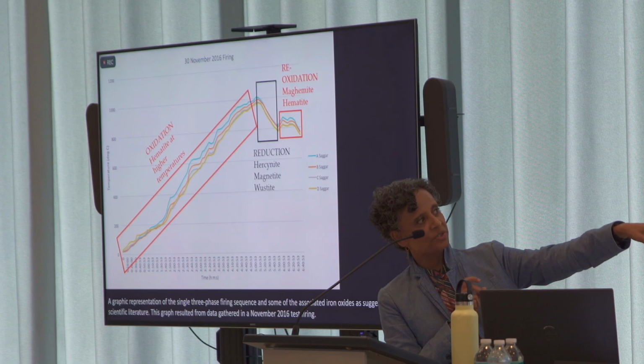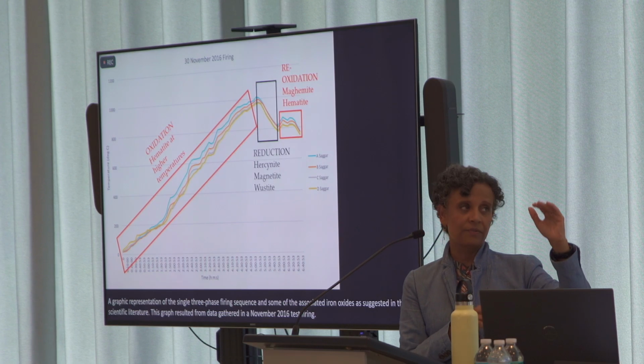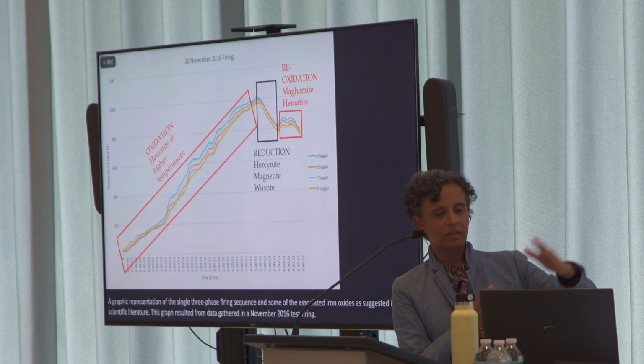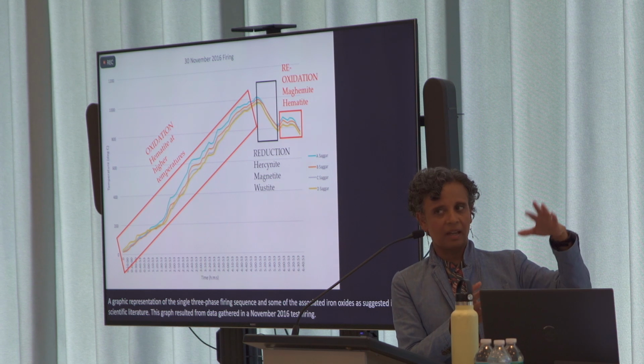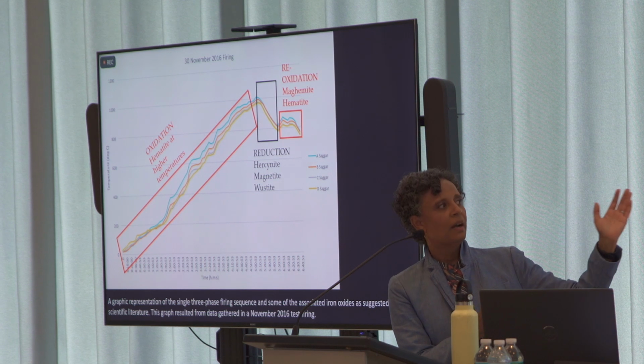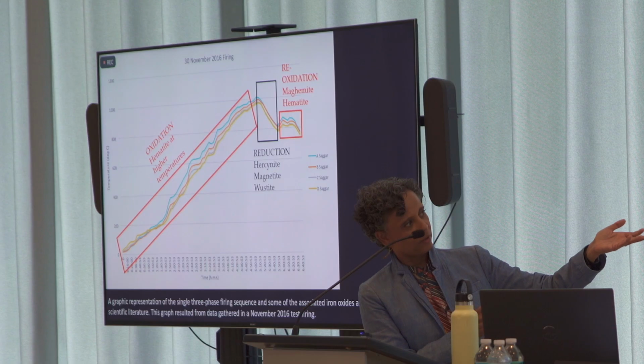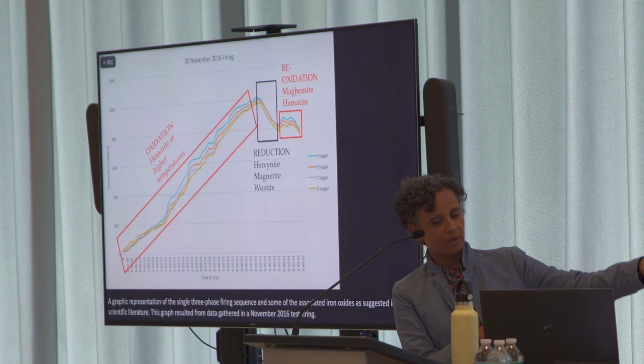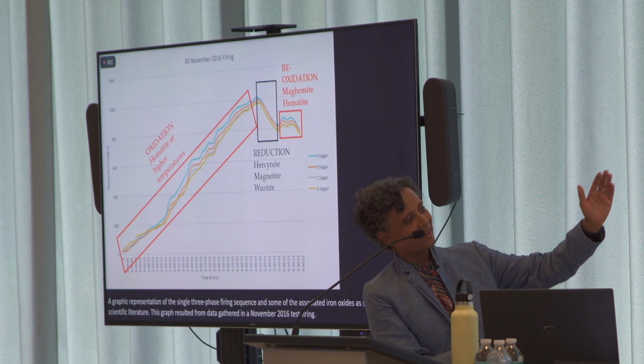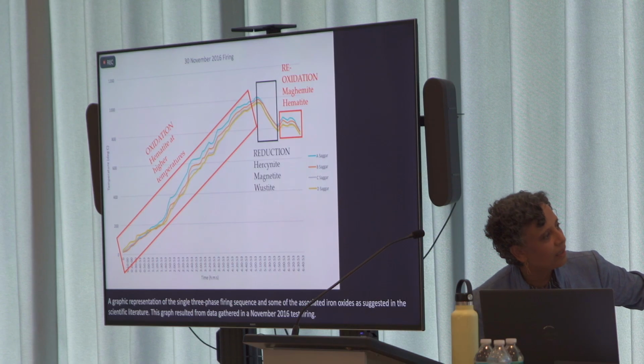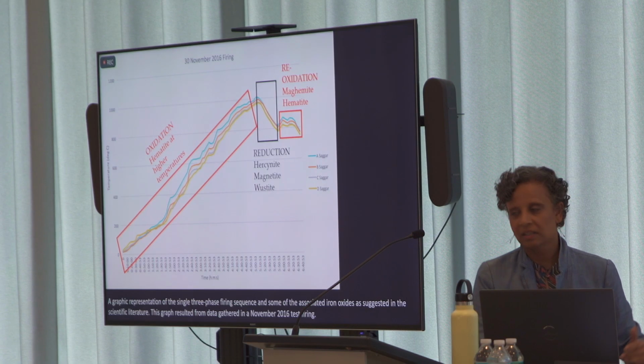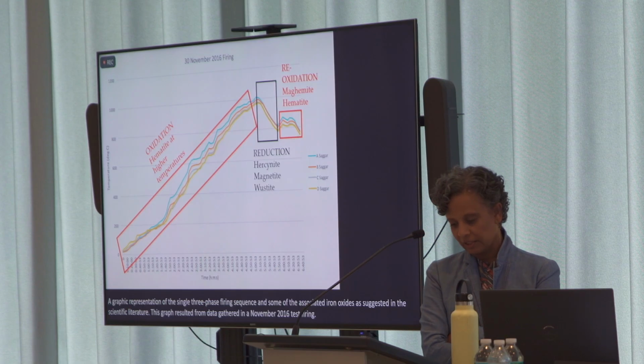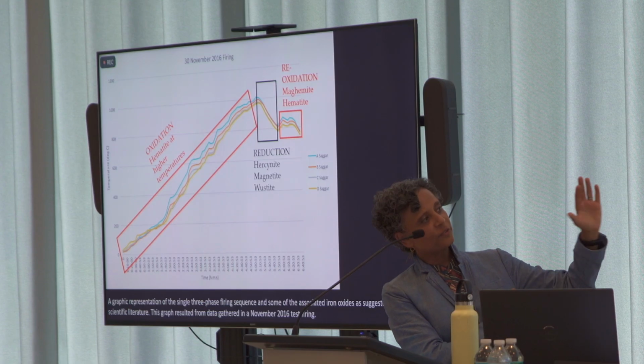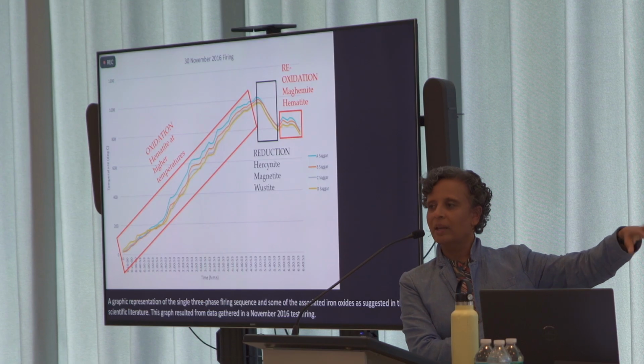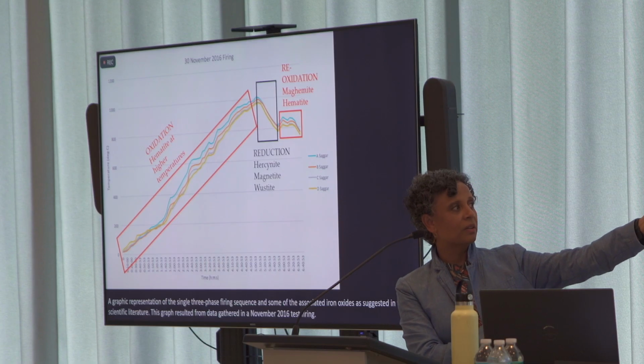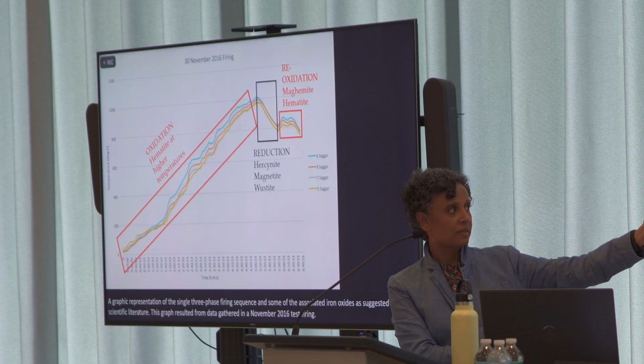of 2016. The different lines are the different shelves of our kiln, which tell you that slightly different temperatures are being reached at each shelf. It was a multi-hour firing process. You can see us going from room temperature, and at its height we were at about 900, a little bit close to 1,000 degrees, slightly over. That first phase is called oxidation, right? We have all this oxygen and we're producing all those nice red iron oxides.